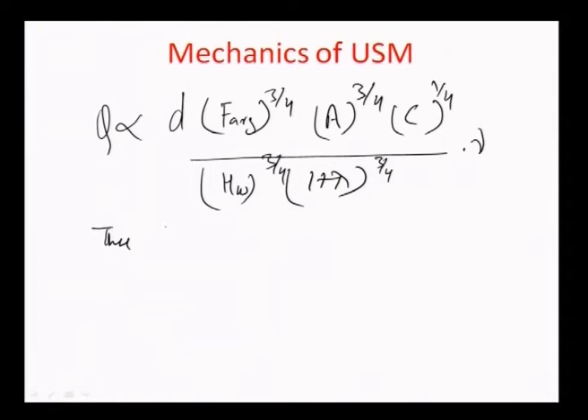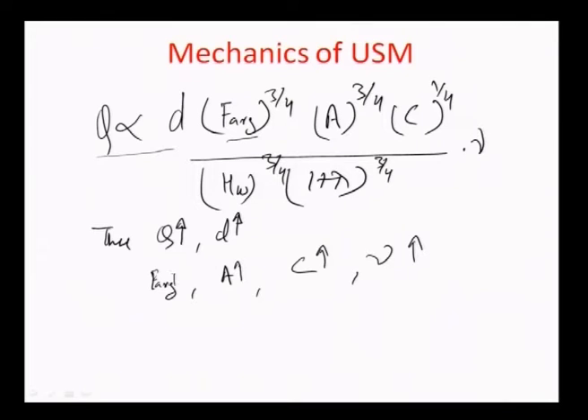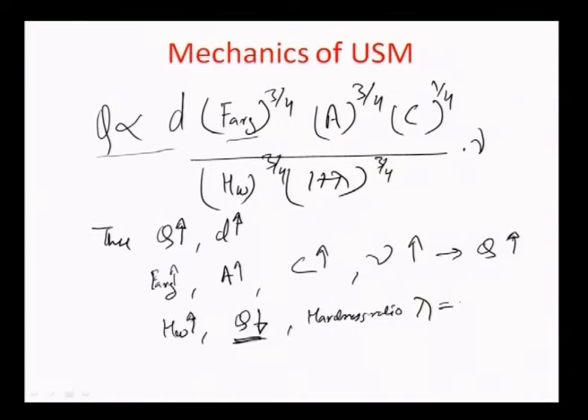And thus, as you know, Q would increase if the grain diameter would increase, obviously because there is a direct proportionality between the two. And supposing all these other parameters like the average force, the amplitude of motion, the concentration of the grain and the average frequency increase, they would significantly impact Q, so Q increases because of them. If the hardness of the workpiece is more, then of course Q falls down, so Q is inversely proportional to it, and so is true about the hardness ratio, and the hardness ratio, as you have earlier defined, is the relationship between the workpiece hardness or flow stress and the tool hardness or stress.